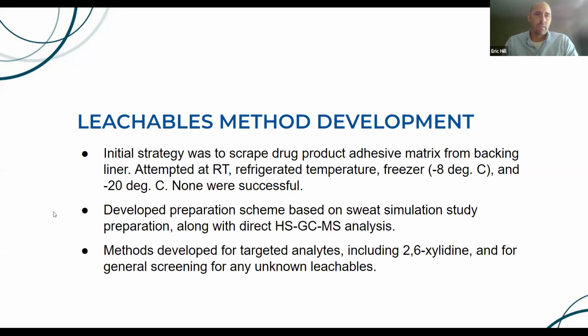Unfortunately, none of them were successful. The adhesive was just too sticky. It was just not really feasible to get a sample off there in any reproducible way. And so we decided to move forward for leachables testing using the scheme that we developed for the sweat simulation study, along with direct headspace analysis. So a little bit of a break from convention with regards to leachables testing, but really with the logistics of this patch and what was available to us, this was really our only option.